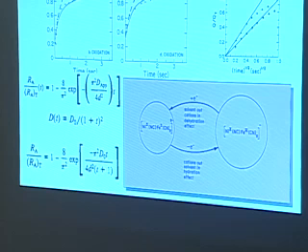Therefore, that cannot be the reason that I'm seeing this shift with different cation in the redox potential. So it really must be the cation itself, not the dehydration of the cation, that's affecting the shift in redox potential. In addition, I could argue, why would I have this time dependence? Well, as this thing is oxidizing and reducing, that lattice is literally expanding and shrinking.